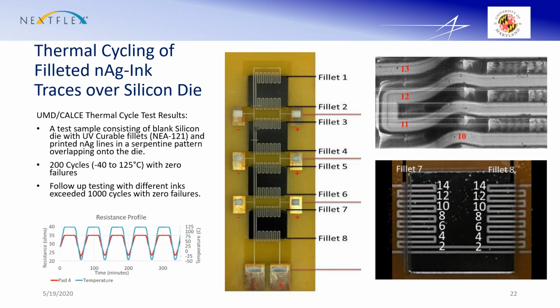It's a UV curable fillet, and it's nice because right as you aerosol spray or dispense it, you have a UV lamp right on the end, so you can cure it as it's coming out or as it's deposited, so you can make these 3D structures. In this case, we're making little edge fillets on the side of the die, like a little 45-degree ramp. Then we would print the silver, and the silver would have these serpentine patterns that go up and down this ramp up to the top of the silicon die, and then down to the printed wiring board and up and down. And this was our daisy chain circuit that we use for reliability.